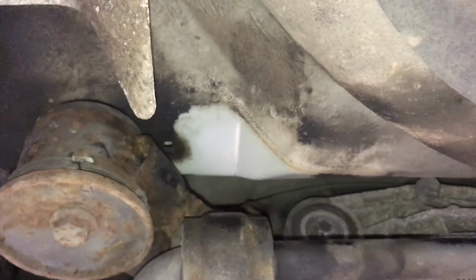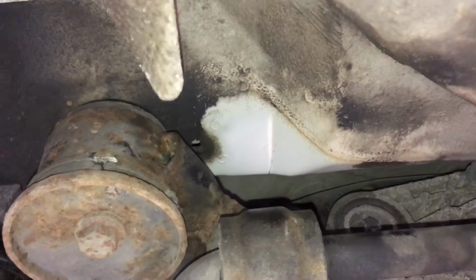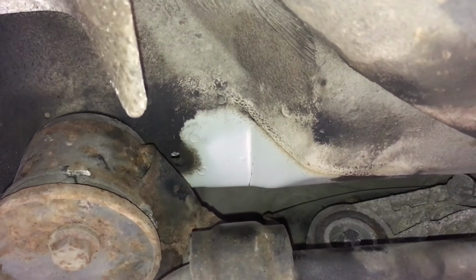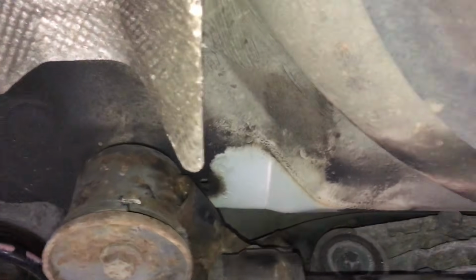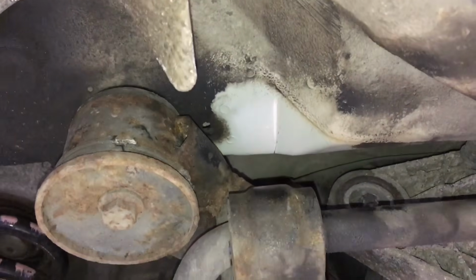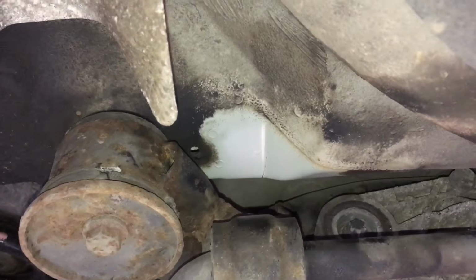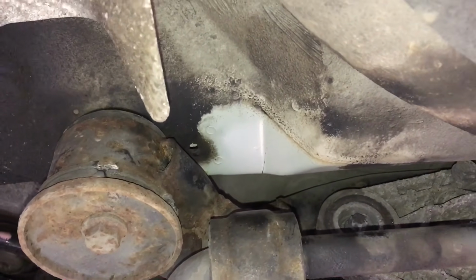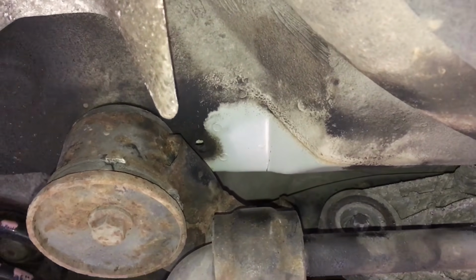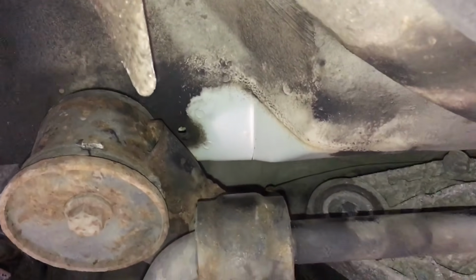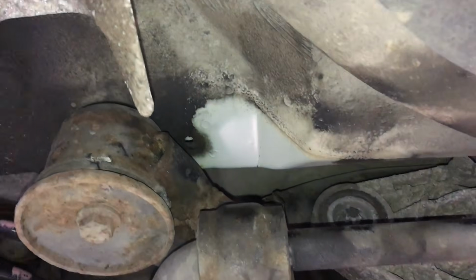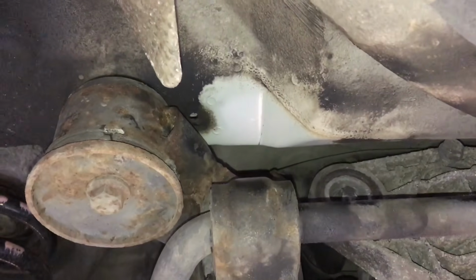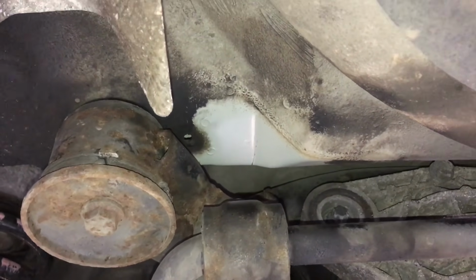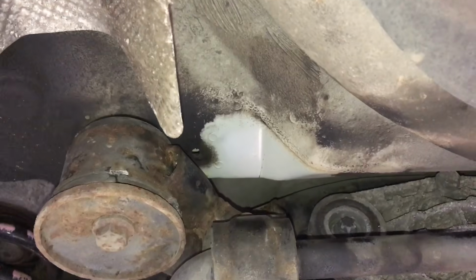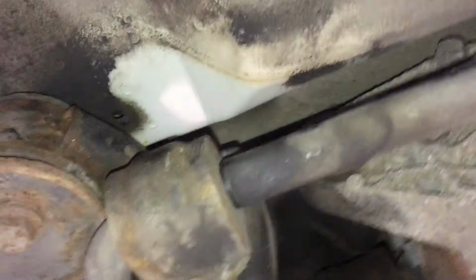It looks like a 3D printed plastic block, and it's bonded very well to all four sides of that cavity to stiffen it up. And traditionally, up until this point, all those vehicles that we've seen are always okay in this corner. They're not suffering with hairline cracks. So for a long time we've been saying that those later cars are okay and much less likely to suffer, which has been true from our evidence. But now that throws everything out of the window, because this is a 2006 model. It does have the later panel with the plastic block inside there, and it's only done 59,000 miles, less than the BMW's 60,000 warranty mileage in the UK. And it is suffering with a big crack up in that location there.